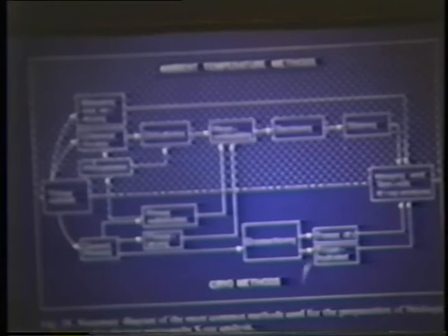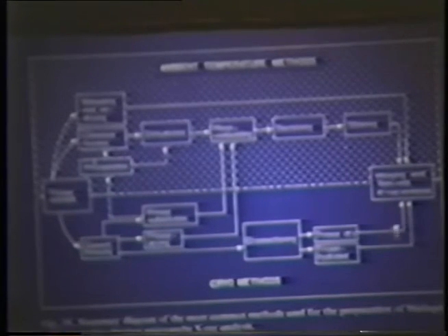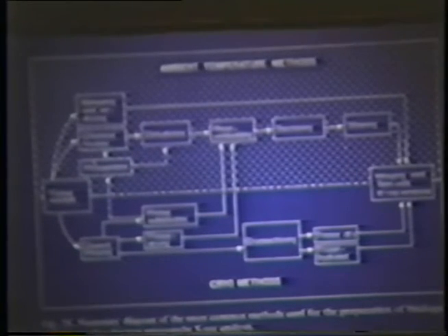You get a material where the elements stay in situ, and you get a material which you can see good morphological information. Generally speaking, if you adopt this particular route, you're going to get very good morphological information, but virtually no valid chemical information. If you go this route, you're going to get valid chemical information, but at the expense of poorer morphological information. Clearly, you would combine both, this for the morphology, and in some cases, certainly do this for the analysis, and in some cases, do this for information about the morphology.